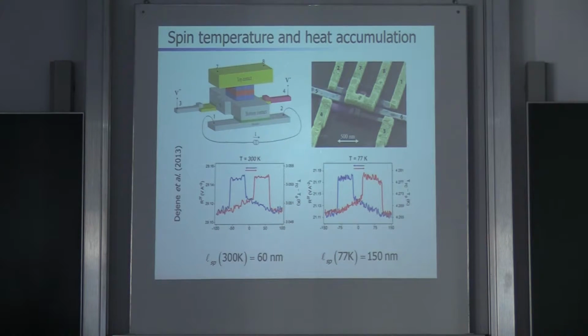Now, purely for the charge current, this would be just a conventional spin valve effect, which basically proves that there is a spin accumulation in the normal metal. These experiments show that there is a difference in the heat conductance, which is a proof that there is a heat accumulation in the normal metal here. These are the experimental traces. This is the magnetic field, which switches the spin valve from parallel to antiparallel. And we see here that the heat conductance of the spin valve is different for the two configurations.